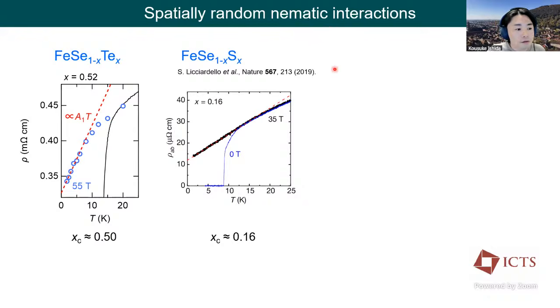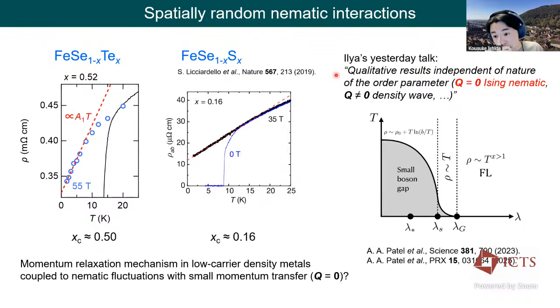This is similar to the ones Ilya and Aavishkar discussed yesterday. But to the best of my knowledge, exact calculations have been performed in the case of antiferromagnetic fluctuations, but are not yet done for spatially random nematic interactions. However, as Ilya showed yesterday, this does not depend on the order parameter. So the spatial random nematic interaction might also stabilize an extended strange metal regime as we observed in iron selenium telluride.